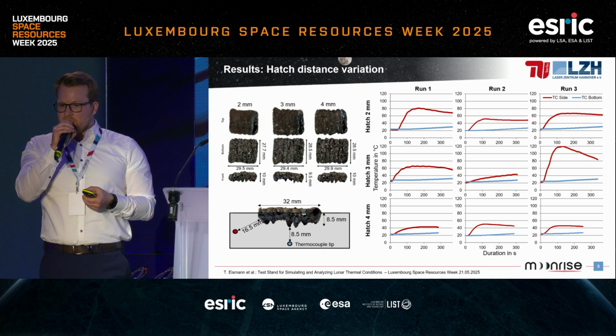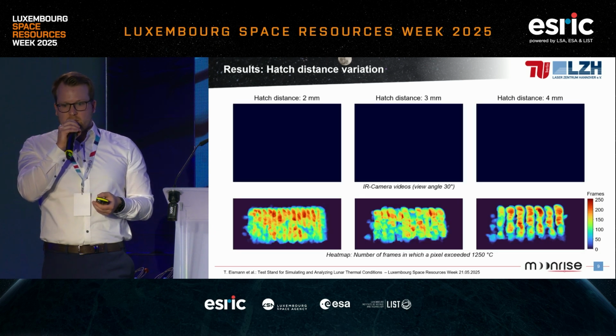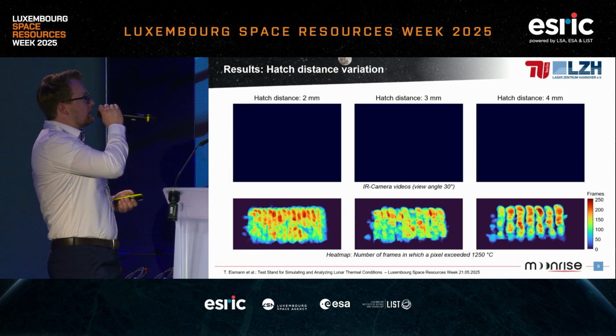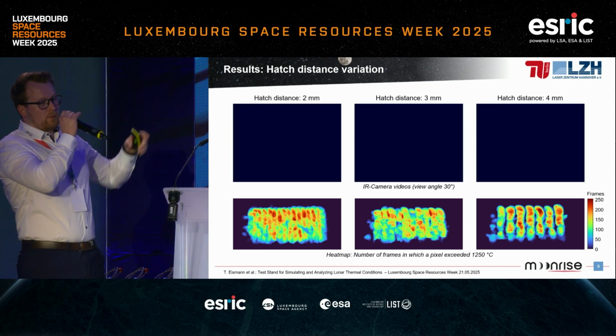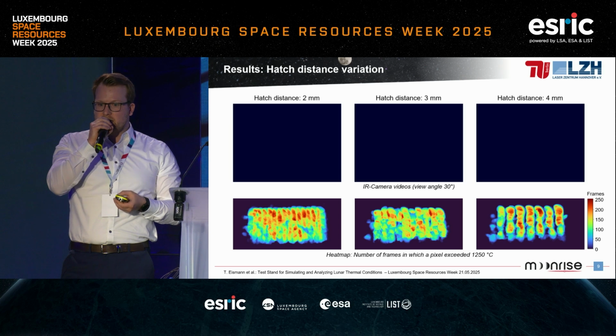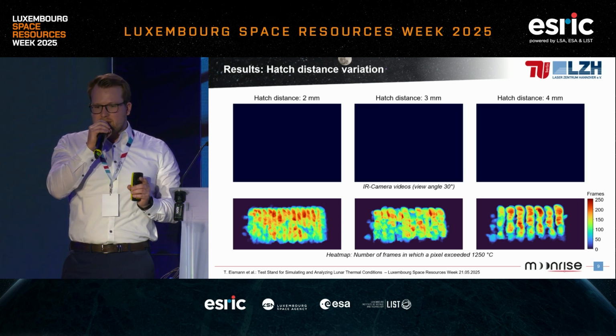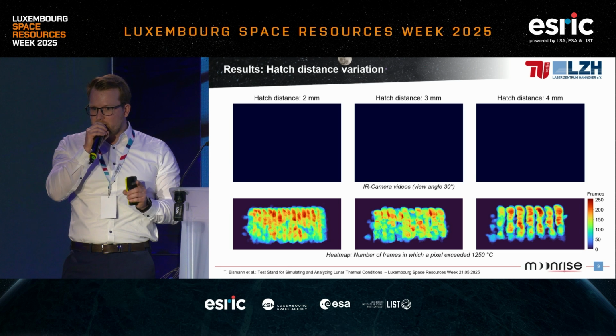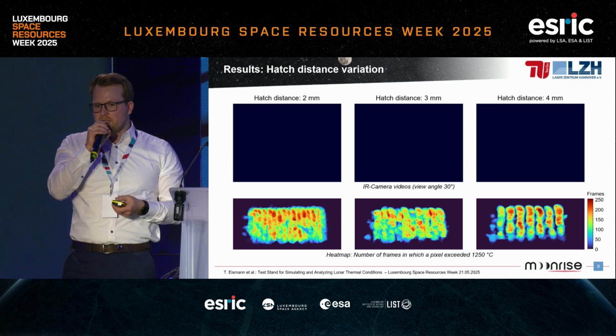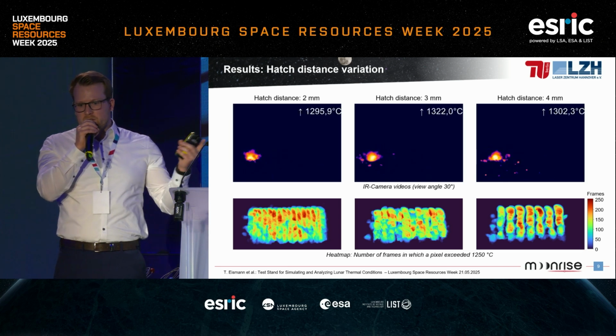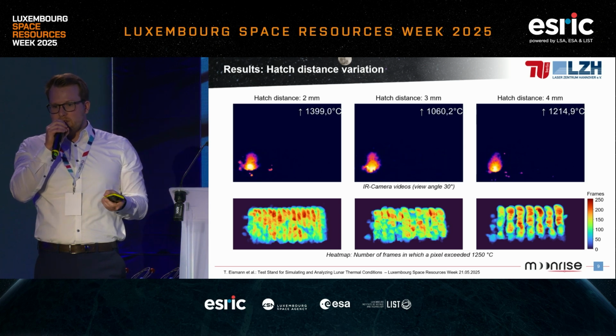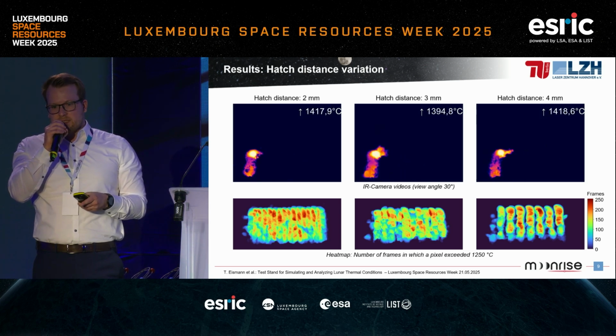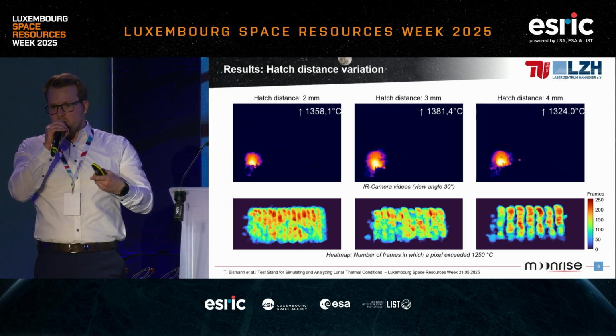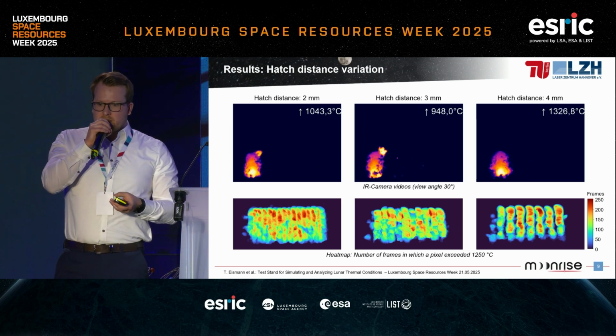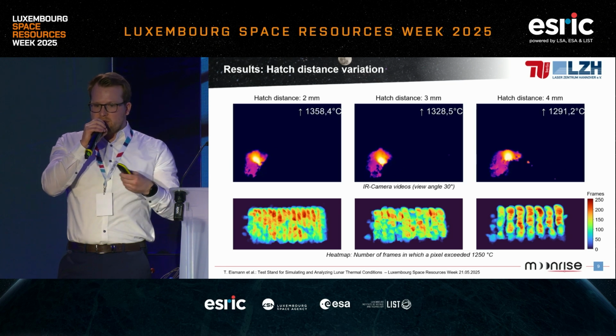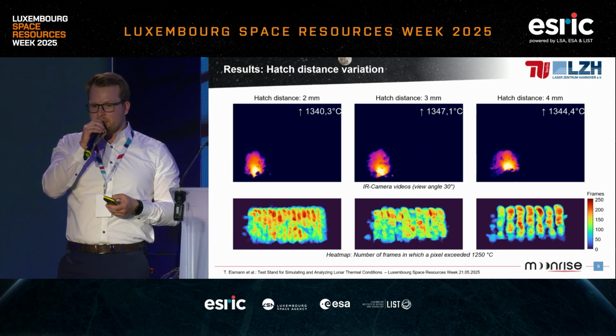And then we also had the infrared camera looking inside the processing zone. And in a moment, you will see in the videos the temperature on the top right. That's the maximum temperature for a time. And this temperature might deviate approximately 5% from the real temperature, but it's still comparable between these videos. And you can see for the first melt track, the temperature is a little bit lower than for the additional melt tracks. And you can see that some of the melt tracks are getting remolten again. And you see that the process gets much more stable the more lines we are melting.